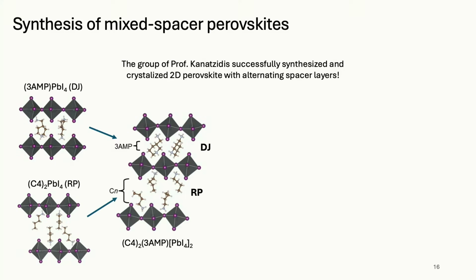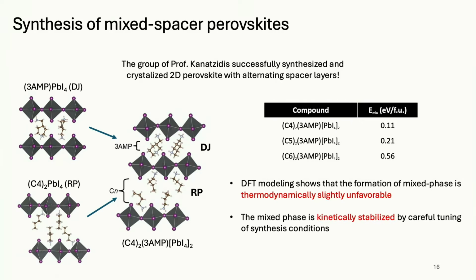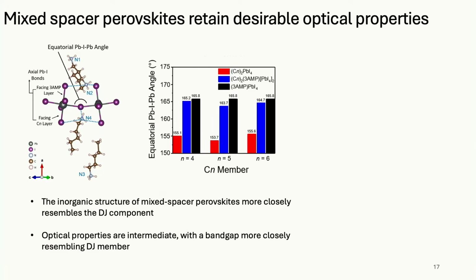Okay, so that's cool. And so we wanted to analyze that. So when we do the calculations, it turns out that the mixing energy is slightly positive. So from a DFT point of view, we would say, no, they would actually like to separate, except that's at 0 temperature. And we think there's an entropy of mixing that's just large enough. And if you orchestrate the kinetics of the reaction conditions, yes, they can get it to form. And they have good evidence that it forms, but we would say it's sort of marginally stable.